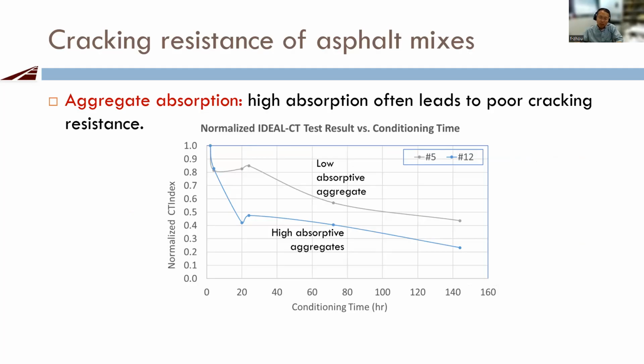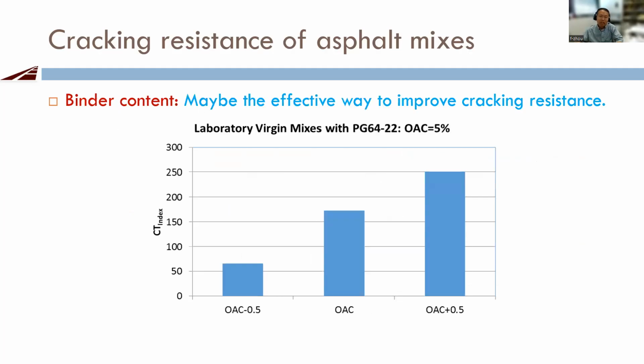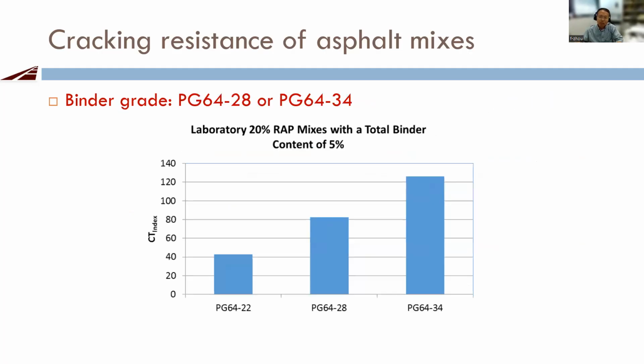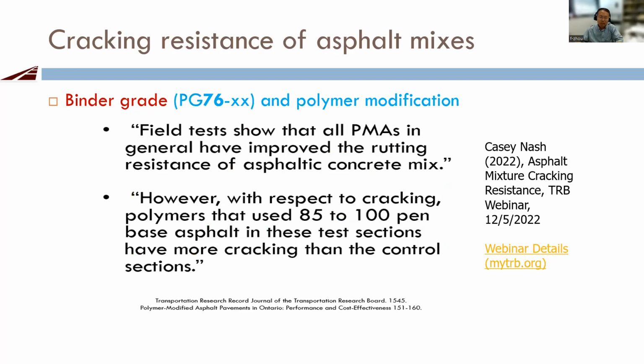The low absorptive aggregates always have better cracking resistance. And the binder content, we all know binder content. If we increase the binder content, you'll significantly improve your cracking resistance. So maybe this is a very effective way to improve your crack resistance. Another thing is the binder grade, 64-22, 64-28, 64-34. Apparently, if you change the lower end of the PG, you can significantly improve your cracking resistance.